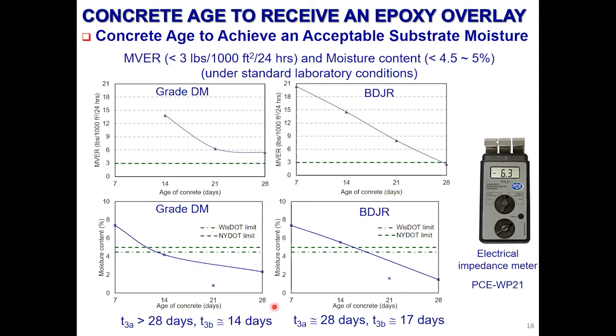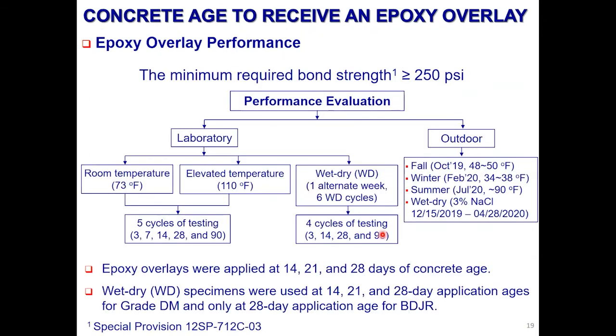In that case, we need to wait 14 days for grade DM and 17 days for BDJR, meaning the mix with type 1 cement. So the last one is to evaluate the performance of the overlay. We want to have a minimum bond strength of 250 PSI. So what we did was we evaluated the bond strength under room temperature and also elevated temperature.